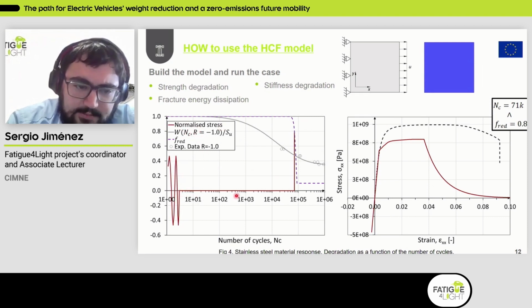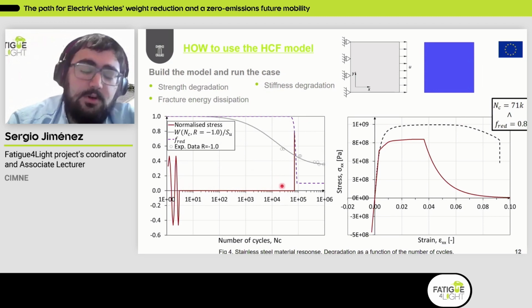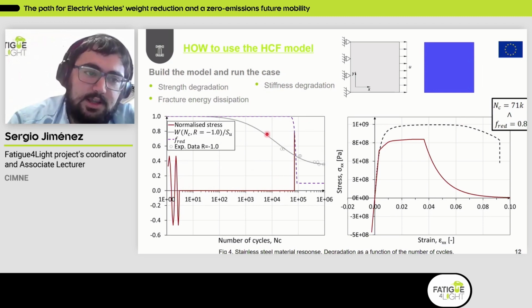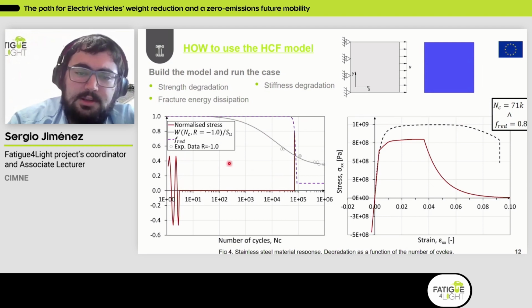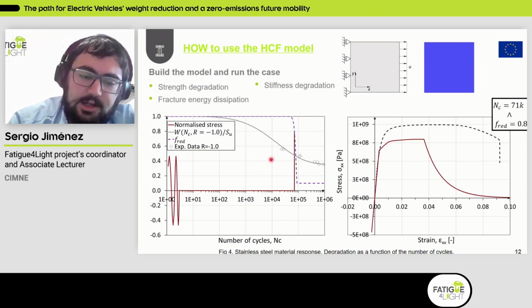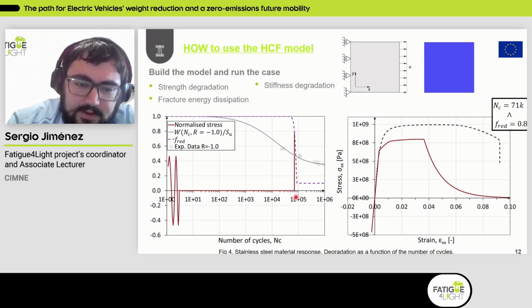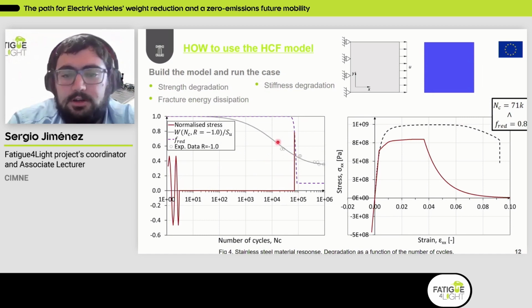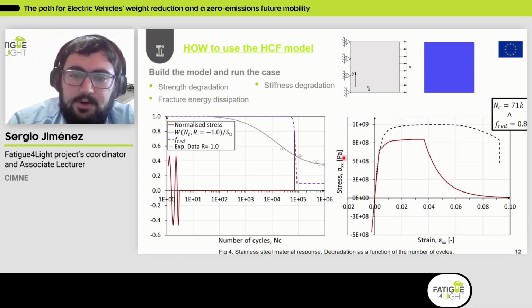You can see here the effect of this advancing time strategy, which allows us to skip all this regime where, of course, strength is being degraded and the fracture energy is being dissipated, but we can skip it because it's not visible at the material level, so we can compute it in another manner. And then we move towards this monotonic load, and you can see here this stress-strain response for the material after these 71,000 cycles.